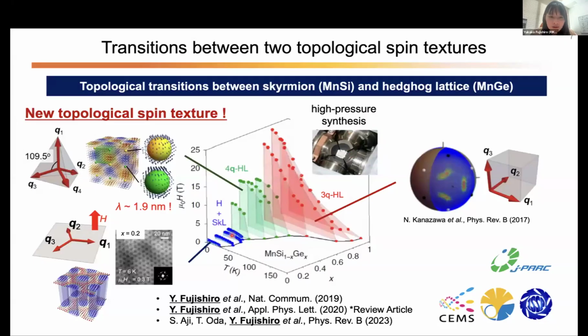This is the temperature and magnetic field phase diagram for various compositions. In the region close to pure manganese silicide, we observed the conventional skyrmion lattice by using Lorentz TEM.